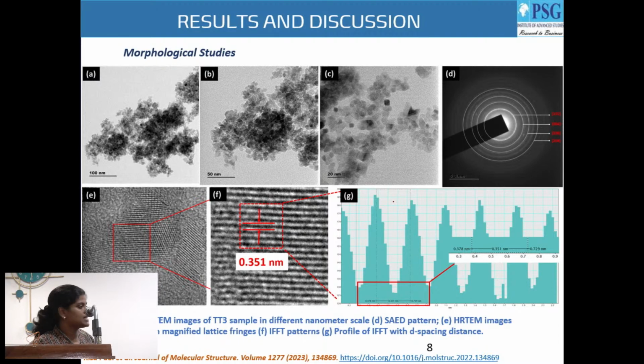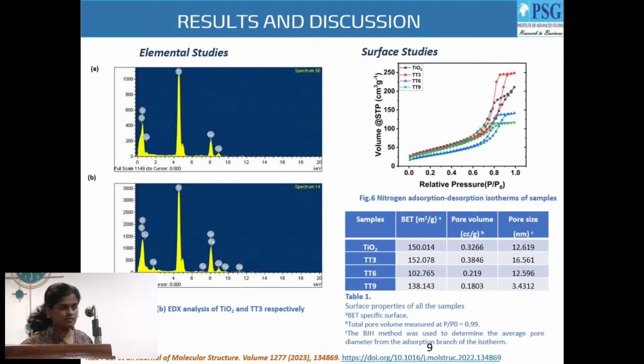These are the morphological studies of tantalum-doped TiO2 with 3 weight percentage. First are the TEM images and the SAED pattern, which confirms the lattice plane of 101 of TiO2 is present in tantalum-doped TiO2. And we have confirmed with IFFT patterns 0.351 nanometer of d-spacing, which agrees with the d-spacing of XRD. This is the profile of the inverse Fourier transform of d-spacing distance.